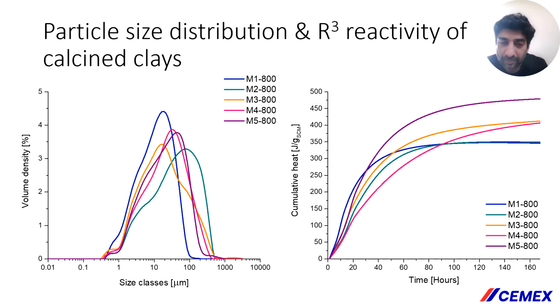Here we have the particle size distribution side by side against the R3 reactivity of calcined clays for cross-reference. Basically, all the calcined clays were subjected to the same conditions in a ball mill, but some clays are naturally harder to grind than others. What we see here is that clay M1800 was the finest of all calcined clays, and M2800 was the coarsest. M3800, M4800, and M5800 showed a comparable particle size distribution.